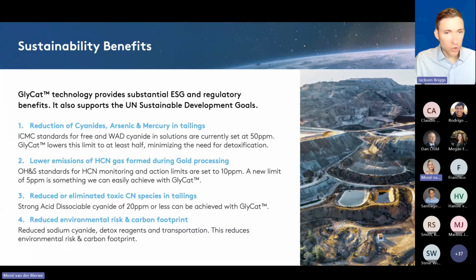So Glycat will lower the overall WAD cyanide that's generated in your final leach tank. And so in a lot of cases, we can reduce or eliminate cyanide detox and just send that material straight out to tailings because it already clears those regulatory limits. Also, lower emissions of HCN gas formed during gold processing. Because cyanide concentration in the solution is lower, there's a lower threshold for pH modification and lower risk of HCN off-gassing if that pH drifts into an unsafe range.